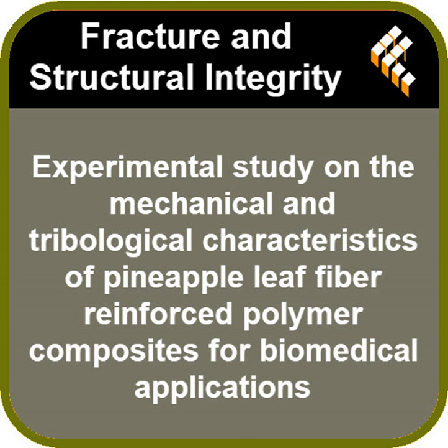Adding more fiber actually reduced the friction coefficient down to 0.51. It was significantly better than just the resin by itself. So the fibers are actually helping to support the load and resist the micro-cutting forces that chew up the surface? It seems so, which makes it durable enough for sliding parts, things like knee or hip supports. It opens up a huge door for prosthetics.